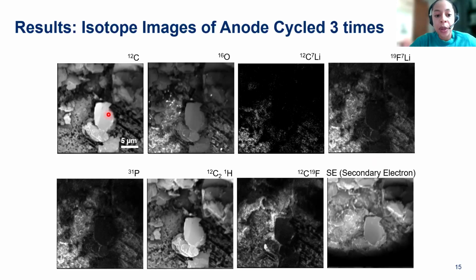And we see here we have a nice graphite flake, and then we have some of the other materials involved in the anode materials, for example carbon black. But we look first at this nice carbon flake, and we see obviously 12C carbon. There's oxygen distributed with a few hot spots along this area. Not very much lithium, 12C7Li signal, just maybe in the corner here.